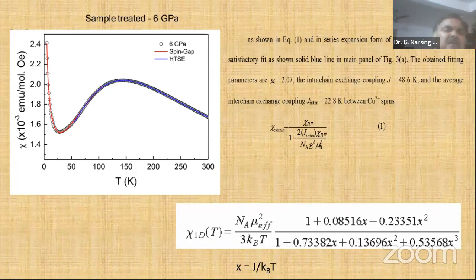So then they said it's only low dimensional magnetism. For low dimensional magnetism, there are a lot of theoretical calculations. You can see this equation. This is a one-dimensional chain equation, depending on x. J is the intra-chain exchange coupling between spins. That is the J value. Depending on this J value, the magnetism will change. This fitting we make in Origin, very easily. So this is the Origin fitting.